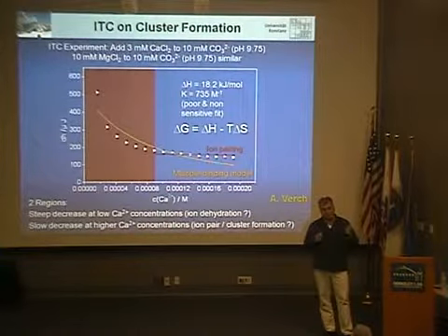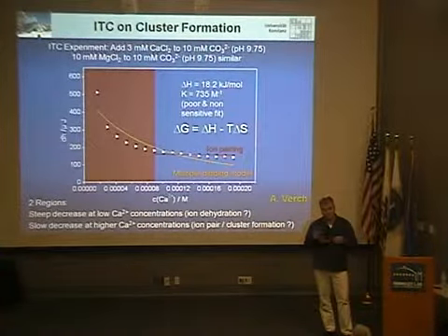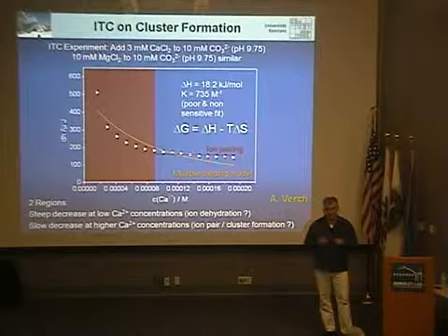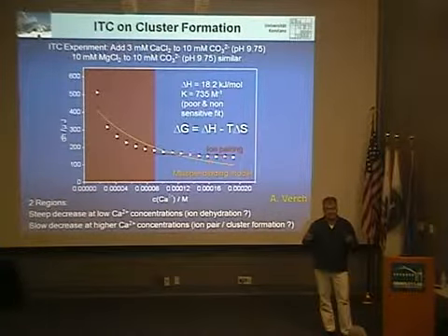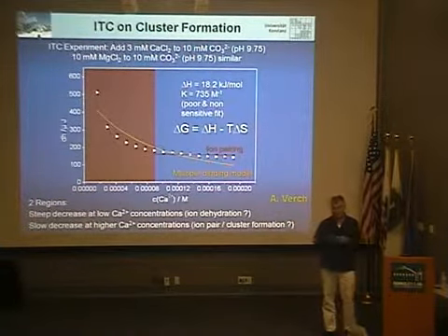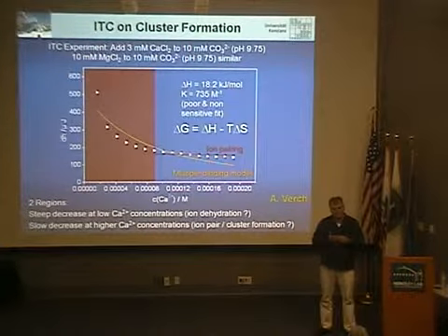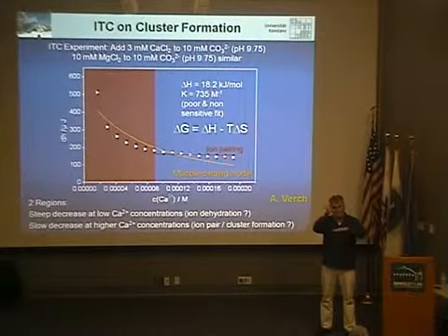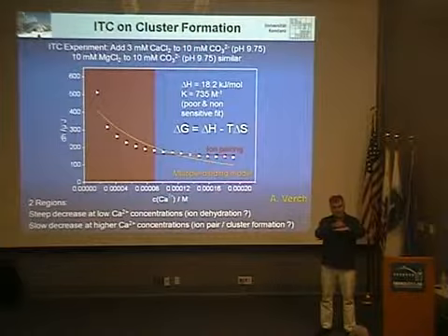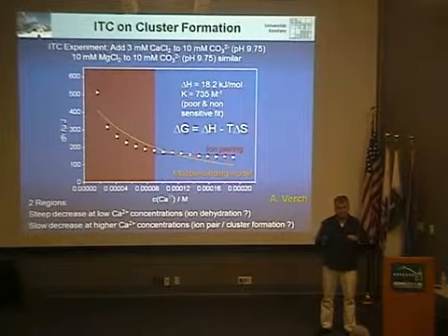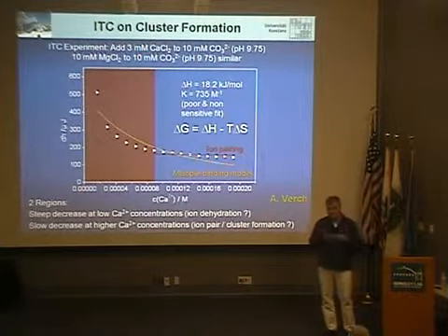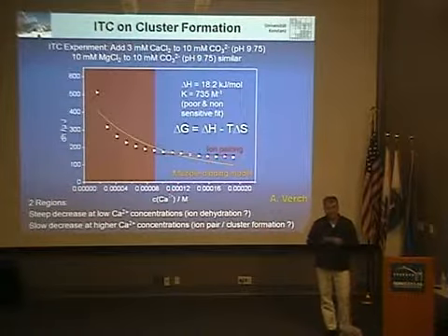We saw clusters in solution by the centrifuge. We did some recent mass spec, and it showed that we at least got 6-mers in the solution. Maybe there are higher oligomers too. So it seems possible that clusters fall from the solution, attach to a surface, and then spread out as a layer. But that's the only experiment which points in that direction, which I know of so far.